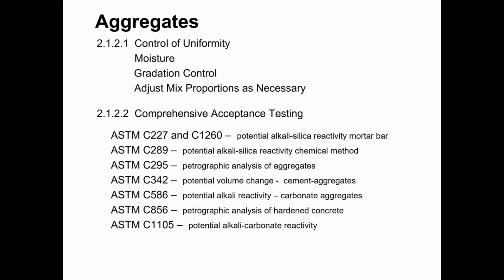Petrographic analyses can be expensive, so if the aggregate supplier is not providing test data and it's up to the plant to get the aggregate tested, then instead of having the petrographic analysis completed, they may do one of these potential reactivity tests just to cut the corner off the testing process and determine whether or not there's any potential reactivity.